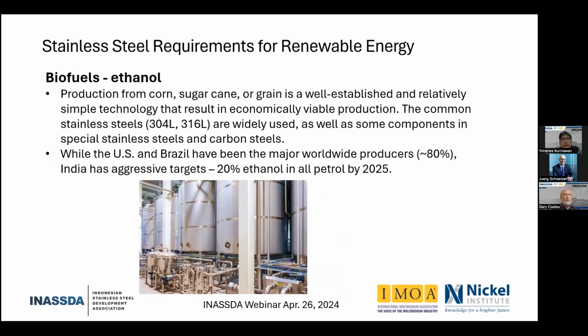The major production today of ethanol as a biofuel comes from either corn, sugarcane, or grains. It's a well-established, relatively simple technology, economically viable. The common stainless steels, 304L, 316L, are widely used, as well as some components in some special stainless steel and carbon steels. But about 95% of the plant is typically 304 or 316.